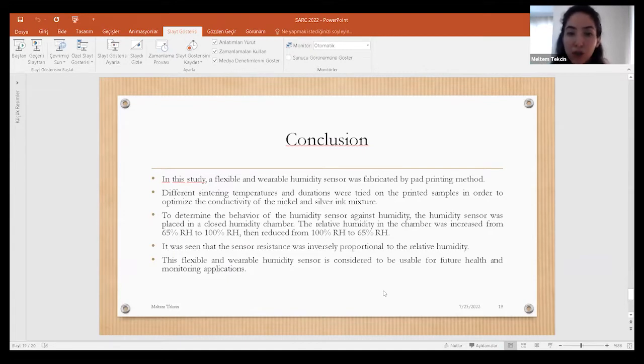To determine the behavior of the humidity sensor against humidity, the sensor was placed in a closed humidity chamber. The relative humidity in the chamber was increased from 65% to 100%, then reduced from 100% to 65%. It was seen that sensor resistance was inversely proportional to the relative humidity. This flexible and wearable humidity sensor is considered usable for future health and monitoring applications.